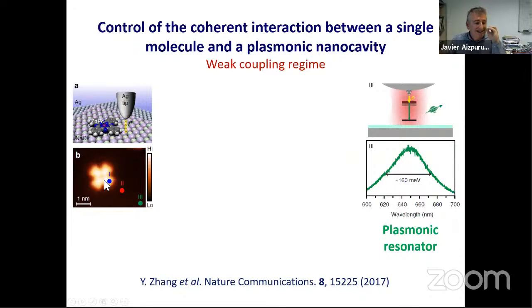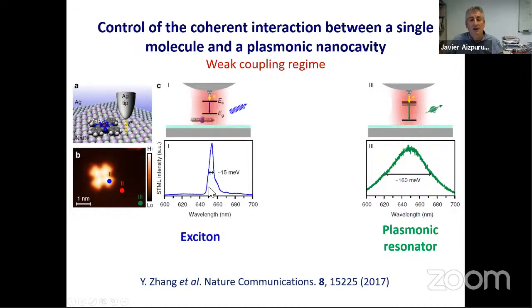Now, if we put and excite directly the tip on top of the molecule, we screen the cavity actually because of the molecule. And what we see is directly the emission from the exciton. This is a much thinner emission from the exciton of the molecule between the excited and the ground state. And you put the detector here and you see it here.